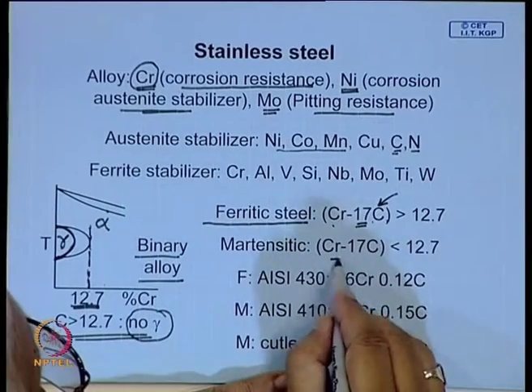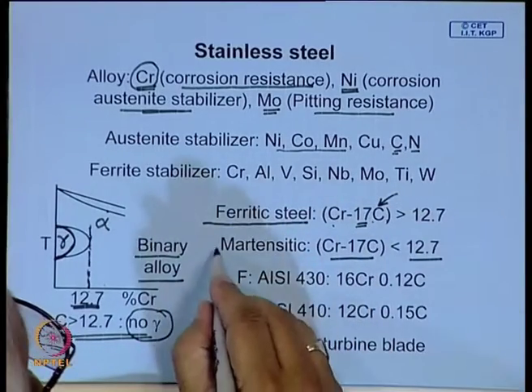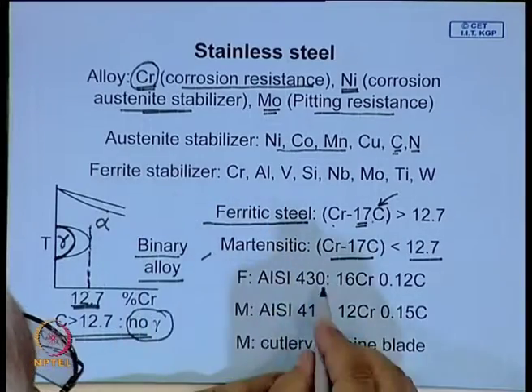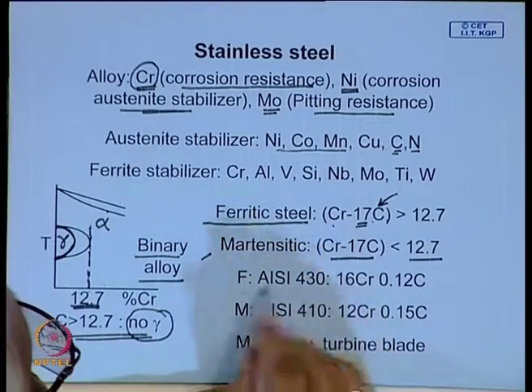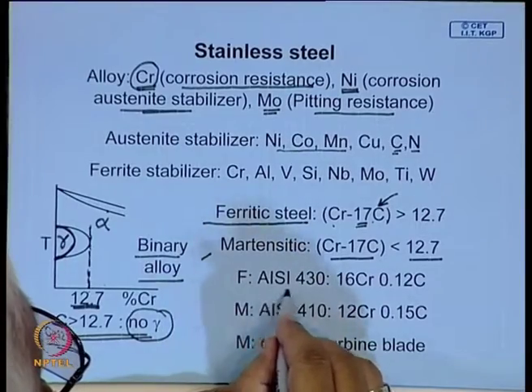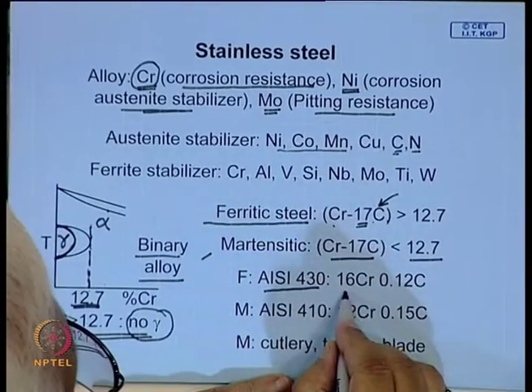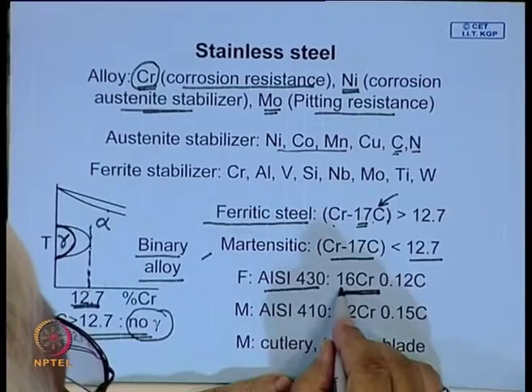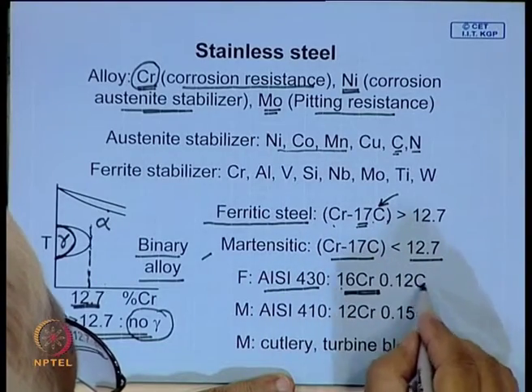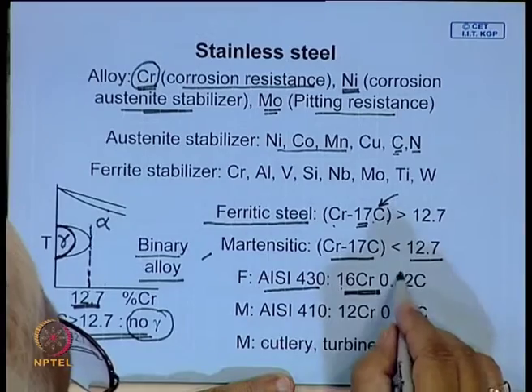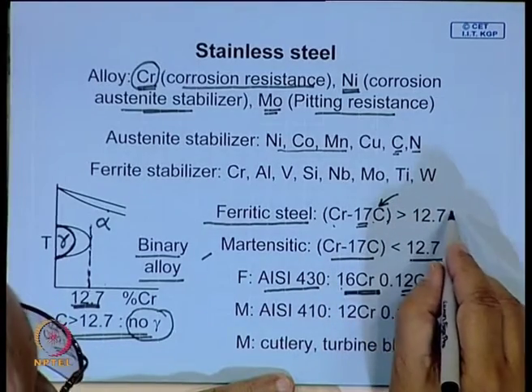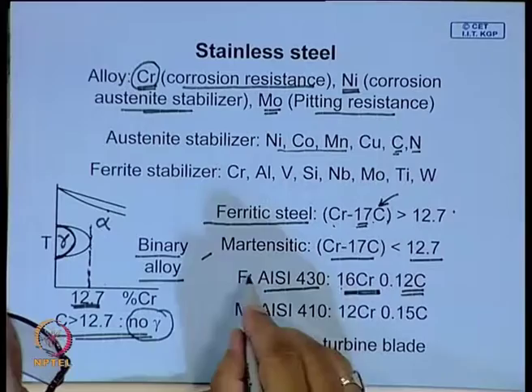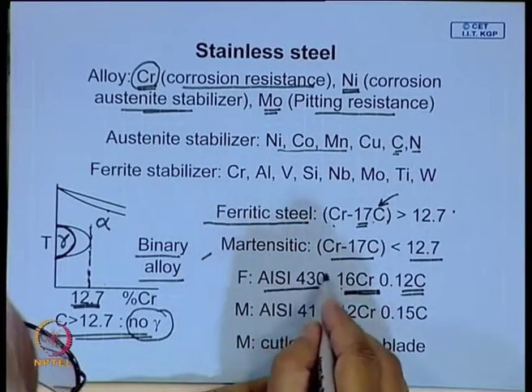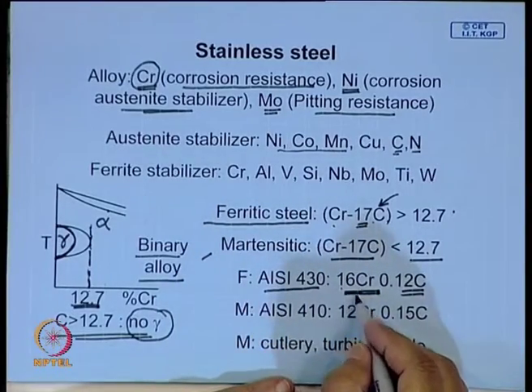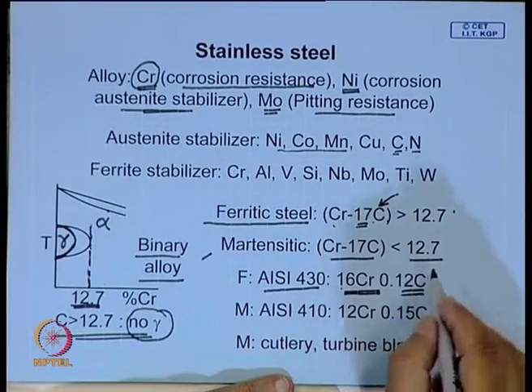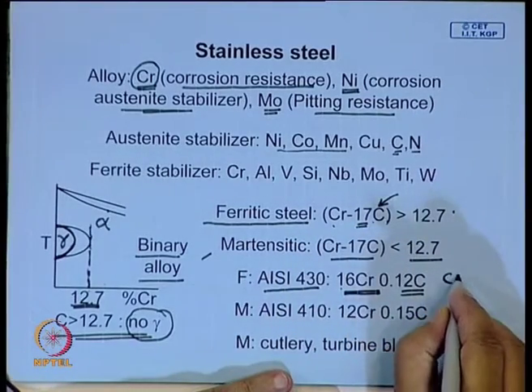And if this is less than this, then we call the steel a martensitic grade, and common ferritic steels and martensitic steel compositions are given. One particular composition is 16 chromium, 0.12 carbon. You will find it will satisfy this relationship, and this will be ferritic. It cannot be given any hardening treatment. Only way you can harden is some solid solution strengthening or cold working.